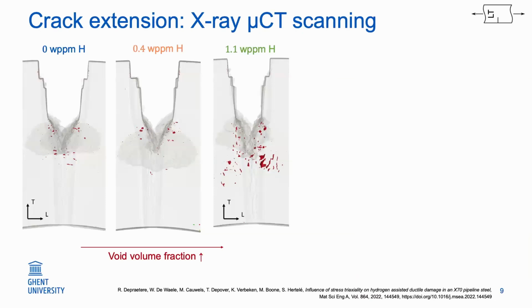Then for the CT scanning, what we can see here is that as the hydrogen content grew bigger, we also see a very pronounced increase in void volume fraction. So we're creating more voids ahead of the crack. These are reconstructed volumes, so the red areas are actually open volume in the specimen.